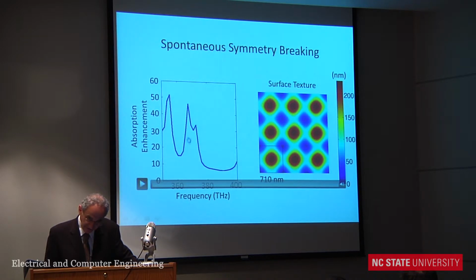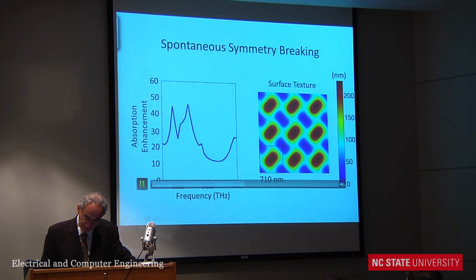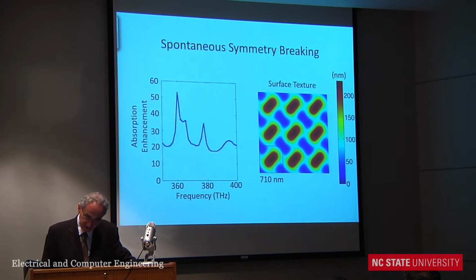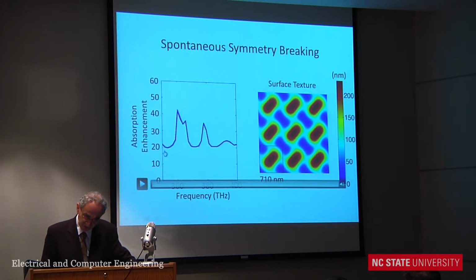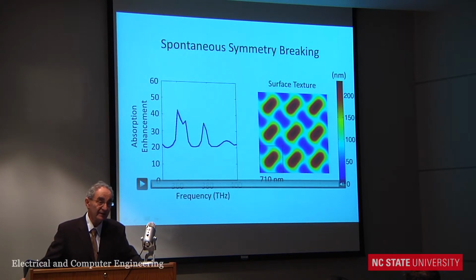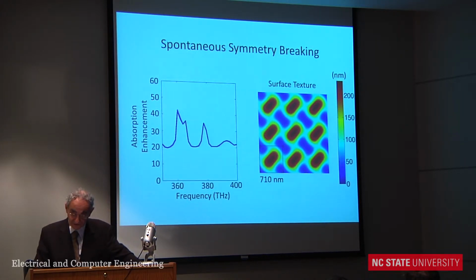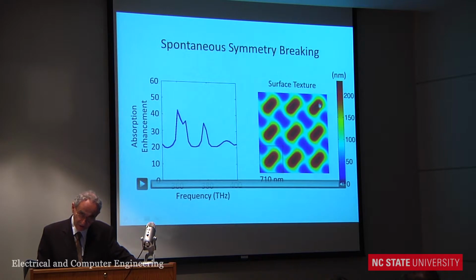And basically on the left side, look, she's trying to get good enhancement over the whole frequency band. Okay, so let's see what happens. So now she's iterating, and this algorithm is constantly trying to improve the worst performing frequency, and here's how it ends. So it ends with about a factor 20 enhancement over what a plane parallel thin film would have been. So it's actually very close to the theoretical limit. And she has interesting things like symmetry breaking. So when you're doing optimization problems, you often get spontaneous symmetry breaking.